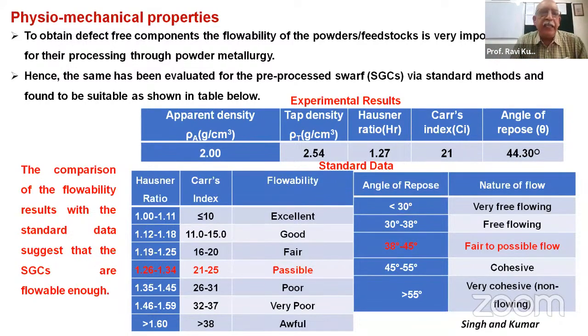If you look at the standard data and consider parameters like the Hausner ratio, if it is in the order of 1 to 1.11 and Carr's index is less than 10, then this material is excellent from the powder metallurgy point of view. As the Hausner ratio and Carr's index increase, it becomes good and then fair. In our case, for this waste material, the Hausner ratio is around 1.26 to 1.34 and Carr's index is 21 to 25. We can say it is a passable material to process. It is not very free flowing; these are the cohesive type of material we have got.